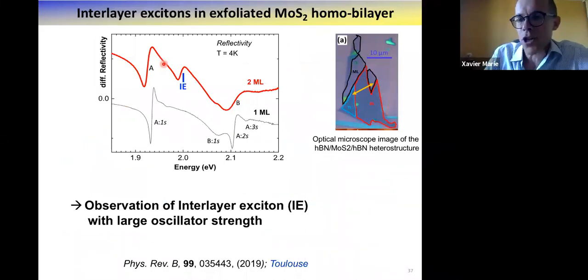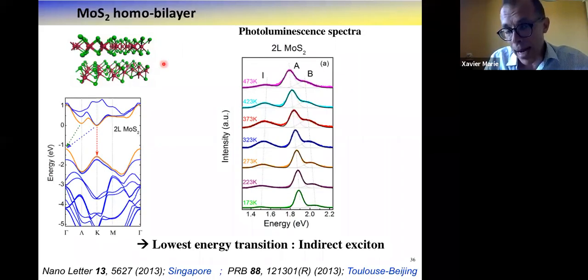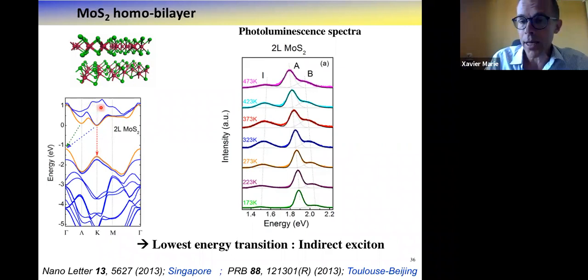Thank you for the question. Indeed, the short answer: only in reflectivity spectra. Why? It's because the MoS2 bilayer is indirect. So the lowest energy transition is the indirect transition. So we do not observe the interlayer exciton in photoluminescence. We do observe it only in reflectivity.